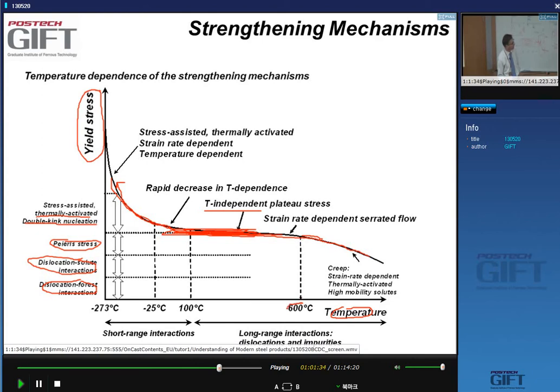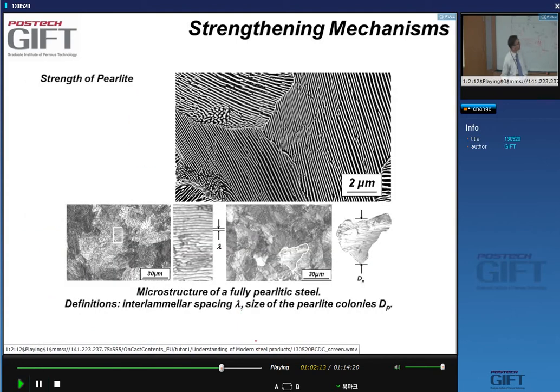Above 600 degrees C, what we see is that the properties are related to creep. At low temperature it is important to realize that we are dealing with short range interactions. Here we deal with longer range interactions between dislocations and impurities. But it's important that you are aware of the fact that there is a temperature dependence to the properties.